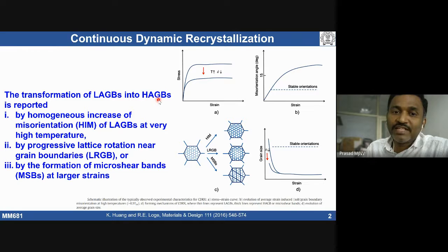High angle grain boundaries can be formed by a homogeneous increase of misorientation. Slowly, the misorientation is going to increase when you deform more and more. At the same time, we may see progressive lattice rotation in some places. Around the boundaries, some rotation can take place that can also lead to formation of high angle grain boundaries. Another thing is micro shear bands. People have shown that around the micro shear bands, we may see formation of high angle grain boundary grains.